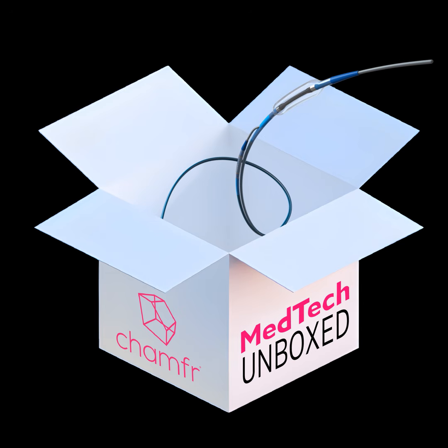Yeah. And then we also find a lot of interesting applications, led by something like laser hypotube, which is now a lot of the architecture going in that direction. For the longest time, the biggest challenge for people using laser hypotube is how do you have a liner that's securely bound in the ID of the laser hypotube. Because it is PTFE, even if you etch it, it doesn't really bond to stainless steel. You have to count on the reflow window, the curve, or the jacket to sink in to bond to it, or you can add a tie layer, but those are not ideal choices because it will still tend to delaminate over time when you flex it.